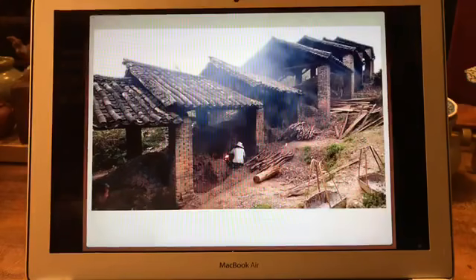So they call it hei gu, which is black bone. And that's because in the dragon kiln there is always a process of cyclic oxidation and reduction. When you throw in fresh wood, the wood will combust, and there will be an oxidation phase. As the wood smolders into charcoal, you start drawing oxygen away during its combustion. That induces a bit of reduction before air re-entry re-oxidizes it again. The dragon kiln firing usually took about 2 weeks for Yixing pots.